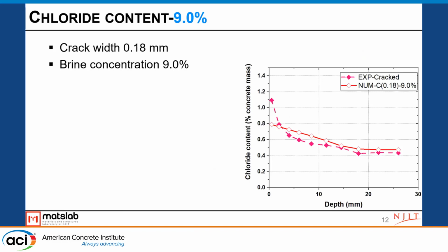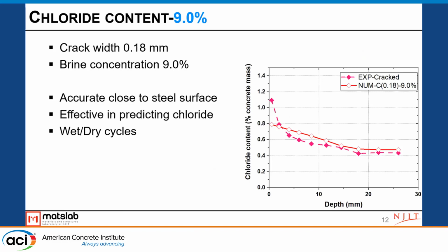What we really want to figure out is, we can say the numerical approach provides a pretty reasonable accuracy in predicting the chloride content, especially at the steel surface, which is of particular interest to us, and is also effective even in this condition where we applied wetting and drying cycles.